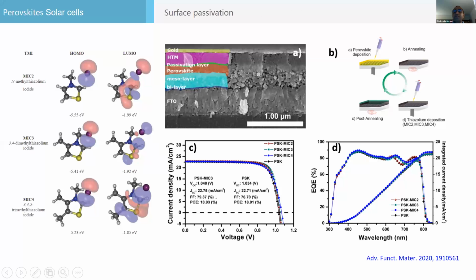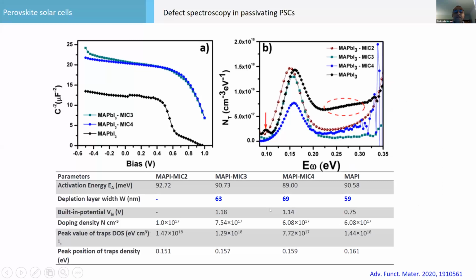And also in the devices, we put a very thin layer of thiazolium iodide on top of methylammonium lead iodide by the spin coating process. This is an IPCE graph, showing how many photons are converting into electrons. So this also gives a little bit higher voltage. And we did admittance spectroscopy to know the defect passivation. So we found that this thiazolium iodide treatment increases the depletion length. If you increase the depletion length, you have a higher voltage, and the built-in potential was a little bit higher.